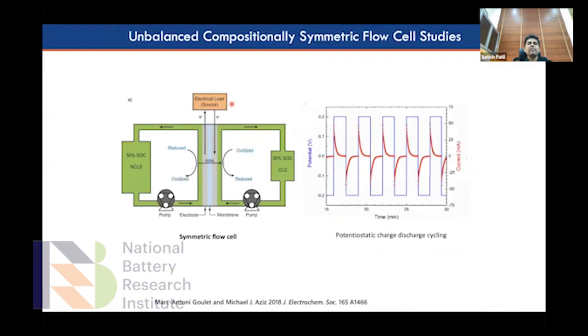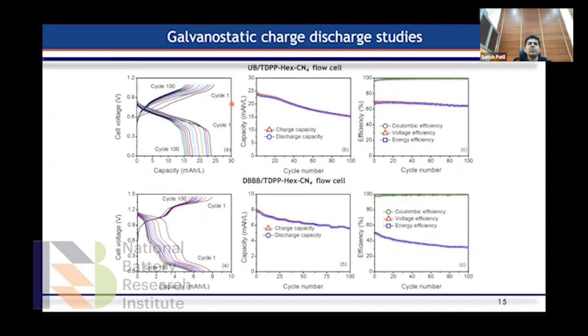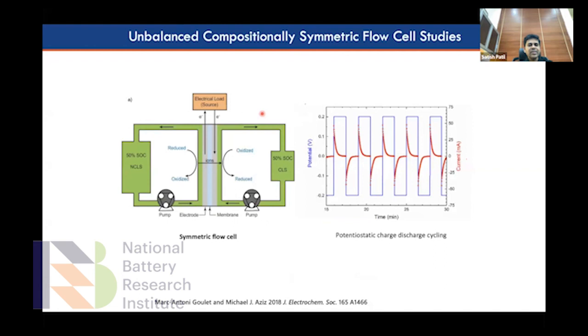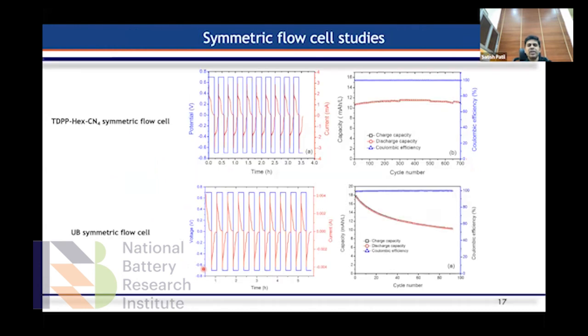Based on that, we did some single cell studies to understand why there is a degradation, or why the battery capacity fades away as we increase the number of cycles. So we did single cell studies here, and we did the charge discharge cycling using both sides a similar material, and a more detailed study to understand the charge discharge cycle. So here is the data for that one. We indeed see this on a UB symmetric flow cell. If you look at this one, this is a flow cell using the material we developed in our lab. Indeed, it shows very stable behavior up to a large number of cycles.